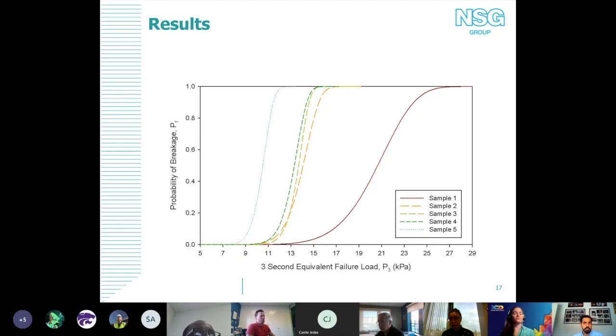Once we applied the frit onto the glass, all of the samples except sample one had frit on them. The coefficient of variation was significantly reduced, so we know it's probably the same reason for mechanical failure that we're seeing in our previous tests. And again, at this mean level, there's not really a clear correlation with regard to what your percent coverage is. It wasn't like 40% reduced it this amount, 50% reduced it a little more, 60% a little bit more. There was no clear answer or solution to show how that worked. But what we saw was significant load resistance reduction in general. So next slide.